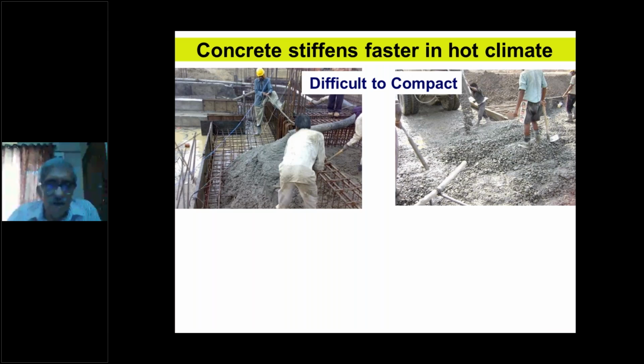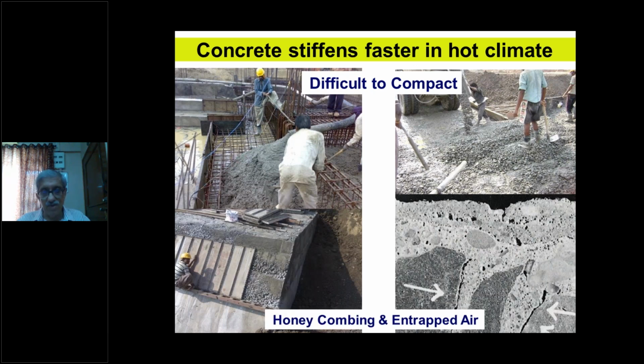Concrete stiffens faster in hot climate and therefore heaps up. So you have to be very careful. You unnecessarily put concentrated load when you are doing slab construction, and you need to spread the concrete or you need to slow down the pumping rate, etc. Honeycombing, entrapped air, all these problems will come if your vibration is not done properly of the concrete. So one has to plan the way you will be vibrating, sufficient number of needle vibrators, etc. will be required, and also you have to be careful that concrete does not heat up.